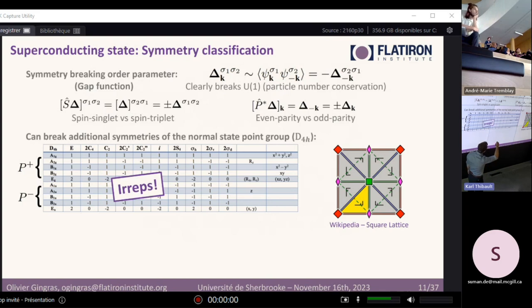Now, number conservation, the number of particles, is broken in the superconducting state, but additional symmetries can be broken. In particular, the symmetries of the normal state point group. In this case, it's D4h. And actually, this is a signature of unconventional superconductivity, because basically in conventional superconductivity, the mediator leads to attraction between the pairs.